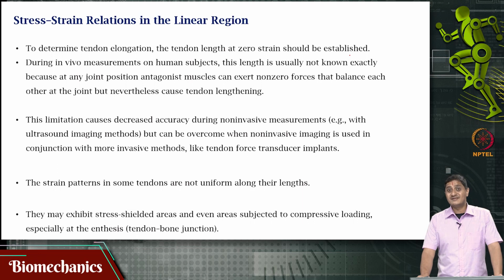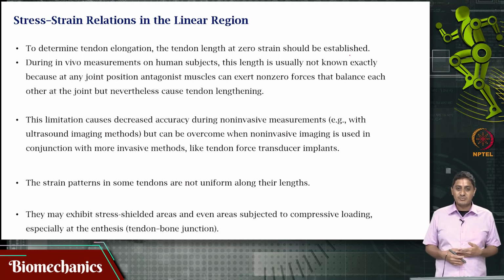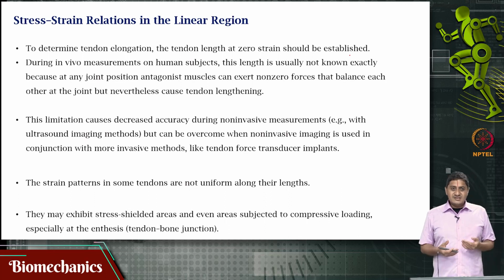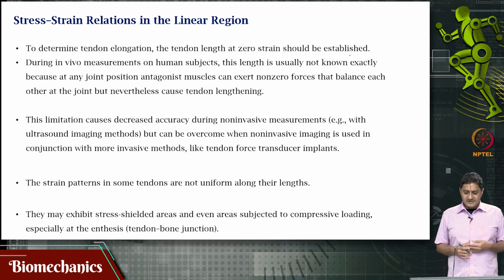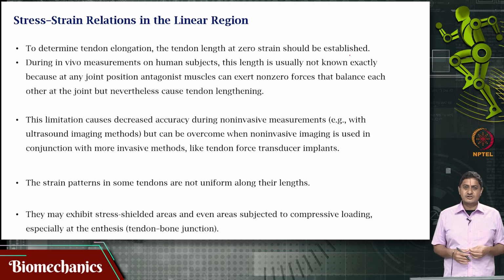So, you actually do not know what the zero length is. There is no active force, there is no actual action being performed, but that does not mean that the tendon length at that point is necessarily 0. So, you do not know where your 0 is. This usually compromises the accuracy of non-invasive measurements, for example, ultrasound methods, ultrasound elastography type of methods.